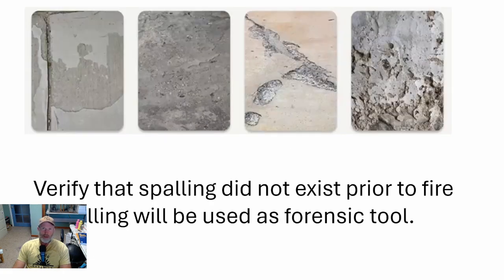One thing during your analysis of a fire investigation: sometimes existing spalling is in place prior to the fire. Witness testimony or samples at other locations can help diagnose that the spalling was not caused by the fire. If you're using spalling as a forensic tool, it's important to validate that it was not there prior to the fire occurring. Expanding water vapor within concrete pressurizes heat-weakened surfaces that have lost their tensile strength due to evaporation of the water in it, and that results in explosive spalling.